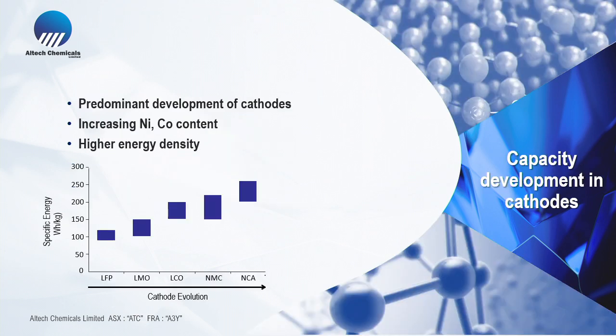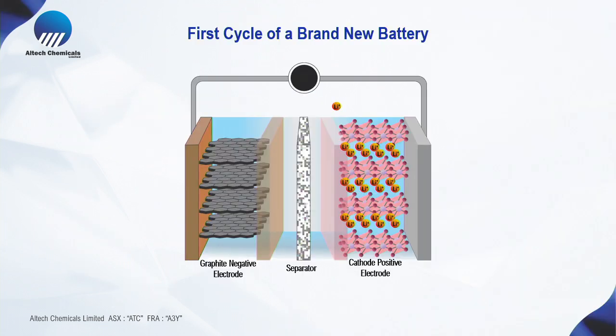in the anode side. Now, it's fair to say that most of the development in the lithium-ion battery has been on the cathode side. So you can see on this graph, it started as lithium iron phosphate cathode, and as you go across, you can see more nickel and cobalt in the cathode component. And so you've got lithium manganese oxide, lithium cobalt oxide, nickel manganese cobalt, etc., NMC. So more nickel and cobalt has been added to the cathode, and it increases the energy density of the battery. So a lot of the work has been done on the cathode side. It's also fair to say that much of the development is also now in the anode side.